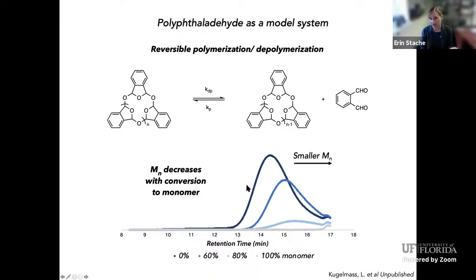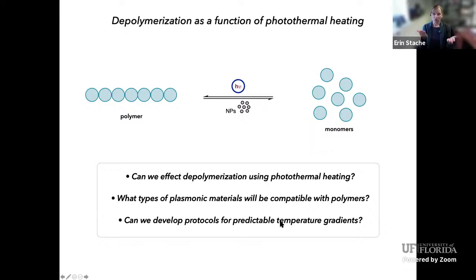And as you might expect, one way to track this is monomer formation, but the other is watching the GPC traces. The molecular weight of the polymer should decrease as you convert it to monomer. So without any monomer, you should have a very large polymer, and then it will decrease to nothing by the end when you have 100% monomer. And so with all this in mind, we have our system, we have our polymer that we want to use, and now we want to ask these questions.